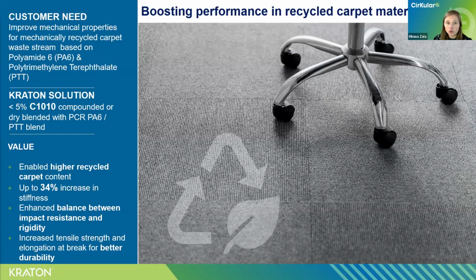We achieved up to 34% increase in stiffness, which is critical for the structural integrity of the application. And the formulation delivered an overall enhanced balance between impact resistance and rigidity. And finally, we saw a significant increase in tensile strength and elongation at break, which translates to better wear resistance and basically longer product life.